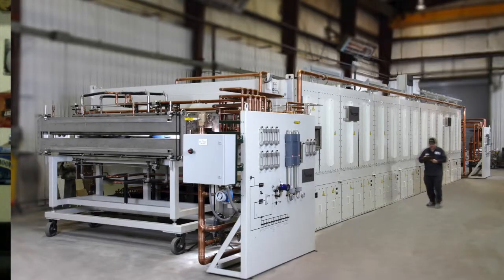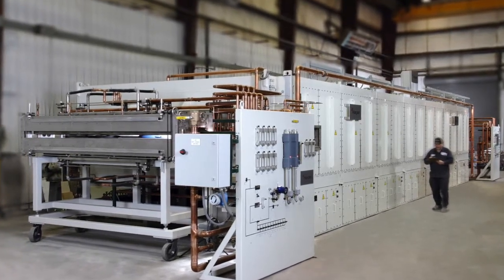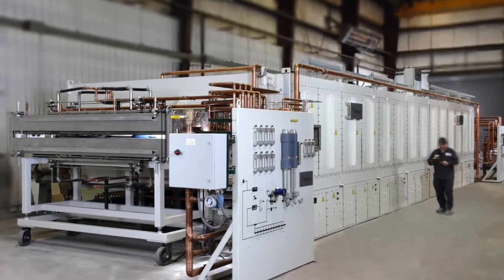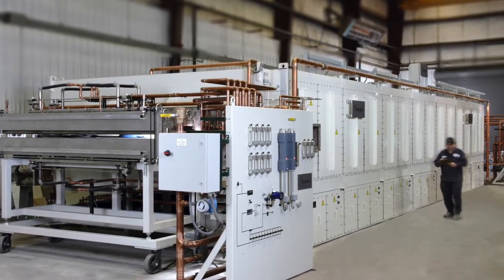After the oxidization process, the fibers undergo another heating process called carbonization. The fibers are sent through a specially designed furnace that progressively increases the internal temperature, with entrance temperatures ranging from 500 to 700 degrees Celsius and exit temperatures ranging from 1200 to 1400 degrees Celsius.